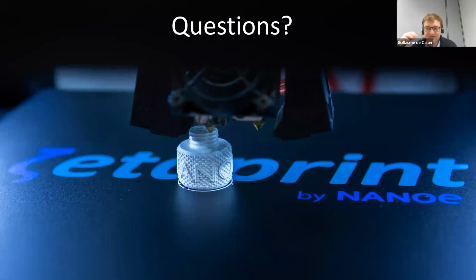One of the reasons for that is that we decided to stay with sintering under argon, or potentially argon with a little bit of hydrogen, and we didn't switch to pure hydrogen, which is a compromise. It's a little bit less good for mechanical properties, but it makes for a much simpler process and much more affordable furnaces. So we decided to stay that way. It's a bit below that, and it's closer to what you would have with MIM.